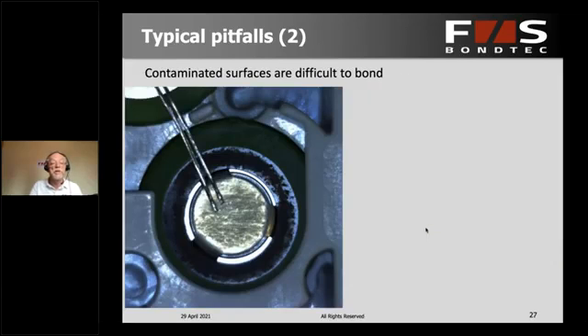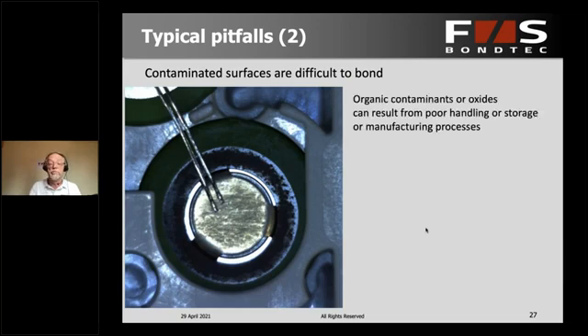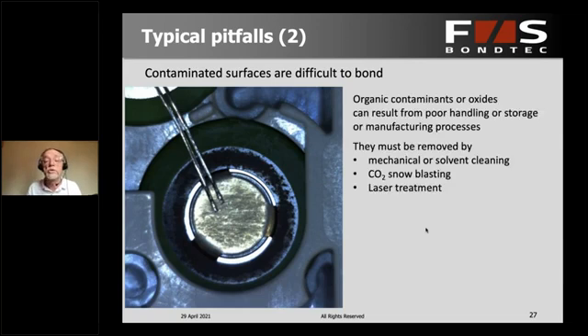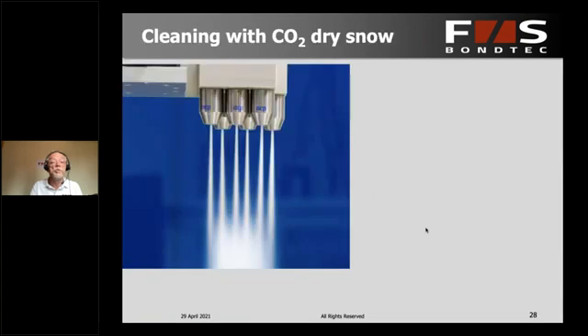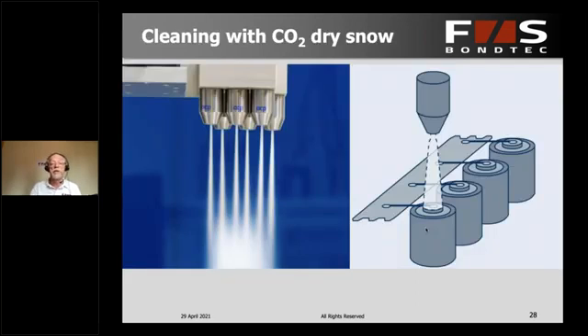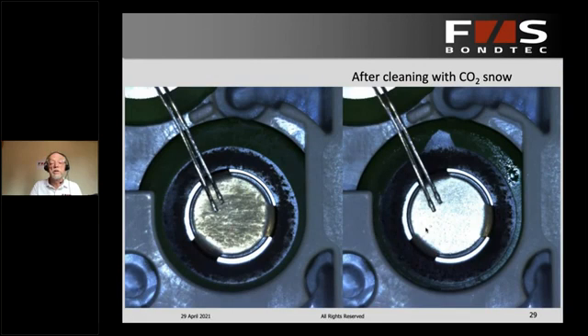The second problem that can happen is that the surfaces are contaminated with all kinds of organic or oxide contaminants, which you have to get rid of, not to kill the process. And that's typically removed by mechanical or solvent cleaning, laser treatment, or CO2 dry snow blasting, which is a process we rather like. You blast dry CO2 snow, which is very easily generated just by blasting it out of a jet. It takes less than a second per spot, and immediately you get very, very clean surfaces. You see before and after cleaning with snow.